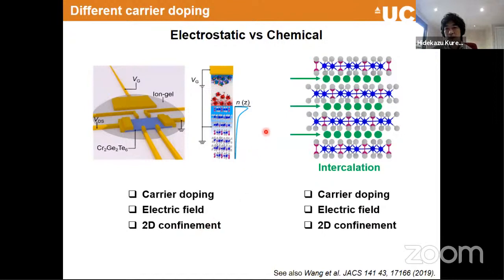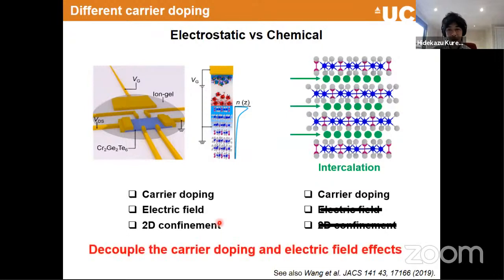Whereas when we look at chemical doping, we simply put alkaline atoms inside this van der Waals gap. That's what we call intercalation in the chemistry language. We can just remove the electric field component and the 2D confinement, and then the effect that we can measure is pretty much coming from charge doping. So by comparing these two results, we wish to understand what this carrier doping does and what the other two do. That's the motivation for this particular experiment.